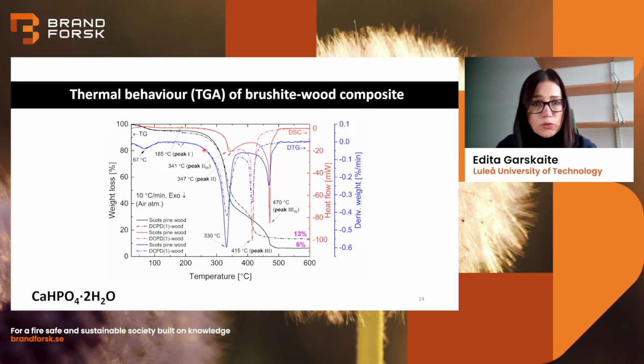Now, another thing we observed: in the wood, which is the red curve, there are two degradation steps, at 347 and 470. However, for mineralized wood, we have one peak which is a little bit shifted to lower temperatures. That can have a little to do with changes in chemical composition of the wood matrix, because when you're treating with solutions, there is a basic or acidic pH, and that interacts with components of wood and probably results in some structural changes.